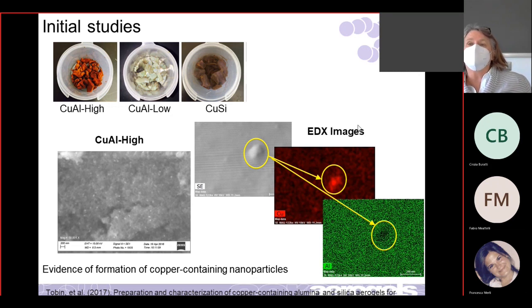So we focused in on one of those particles here, and this is sort of the SEM image. The scale on these is 200 nanometers also. So we focused in on that, and then we looked at, is there any copper there? And sure enough, that spot is bright red. So this is the copper image showing you copper. There's copper also in the backbone, but here it's clearly copper. And if you look at alumina, everything else is alumina, and there's less alumina there. So we didn't have any idea what we were getting, and we found we were forming these nanoparticles in the material. So that was good, just finding that out.